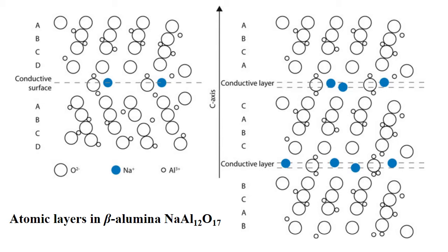The densely packed layers are called spinel blocks. The loosely packed layers are called conductive surfaces. These layers are composed of layers of oxygen ions paired with aluminum ions. The spinel blocks are connected by the conductive surfaces. As shown in the figure, mobile sodium ions, the blue colored circles, diffuse through the conductive layers which are perpendicular to the c-axis. Because of its sodium ion conducting characteristics, the separator is used as a membrane in the sodium-sulfur battery. Here it resembles a cylindrical cup filled with liquid sodium.